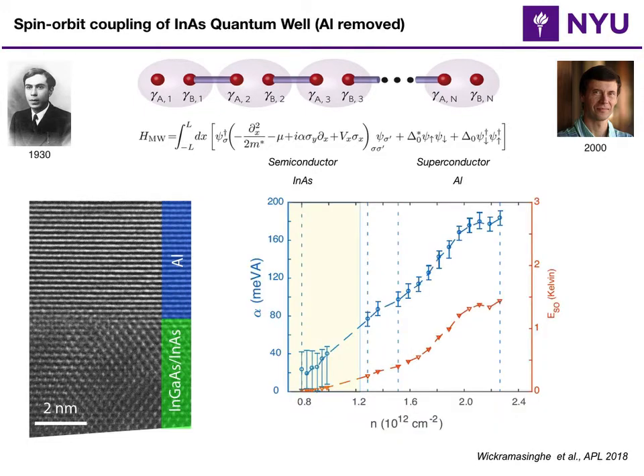For spin-orbit coupling, we have looked at the weak anti-localization signal that these indium arsenide quantum wells show near the surface. And indeed, there is a very high density dependence to this Rashba parameter. If you look at the left axis of this graph, below 1e12 density, there is really not much of a signal that we can pick up from the Rashba parameter. But once you increase the density, it really goes up fast.